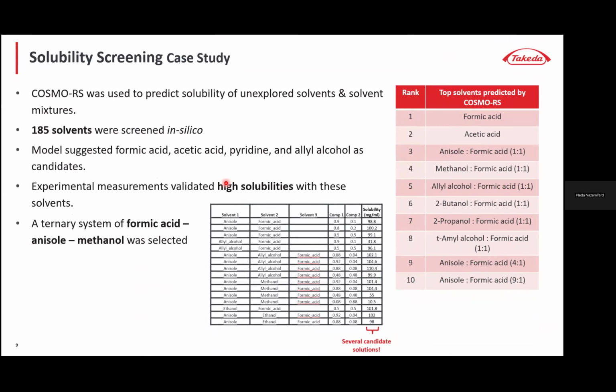Starting with no data, COSMO-RS was used to predict solubility in unexplored solvents. So we looked at 185 solvents in a very short time. And then the solubility model suggested formic acid, acetic acid, pyridine, and allyl alcohol as some of the good candidates. And these are not some of the typical solvents that we usually look at.